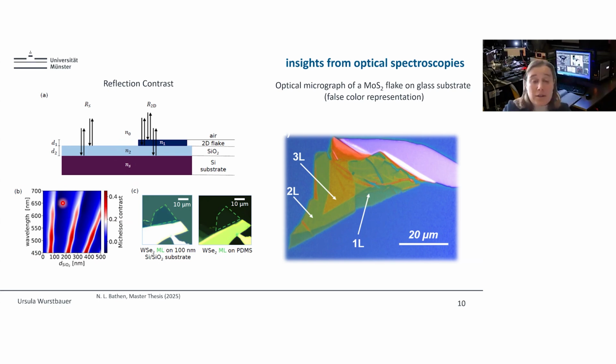And not only the contrast, but also if you do any optical measurement, PL spectroscopy, Raman, reflectance, we get an extremely poor signal. So meaning we have a light guiding effect, and the light is then really trapped within the layer stack and does not come out such that we can observe it. So here you can see that it's already an insight into what we can learn about the material, because the refractive indices of the individual materials all contribute, and of course the individual thicknesses of the thin layers.